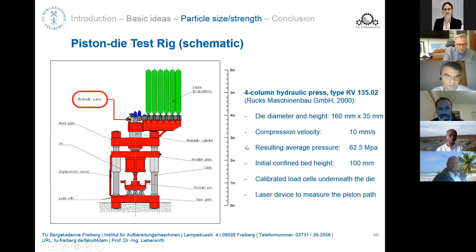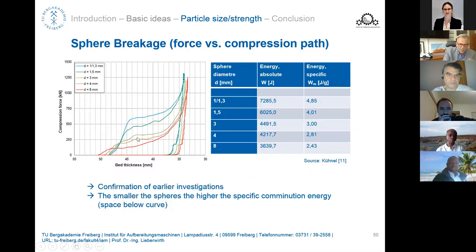The test was done here on this piston die test rig, which we had seen earlier already, at least the die was in the photo. So the compression velocity was fixed. The initial confined bed height was 100 millimeters. The die diameter in this case was chosen to be 160 millimeters.